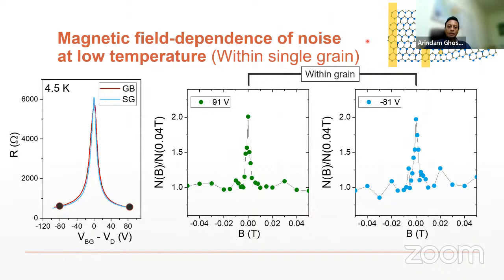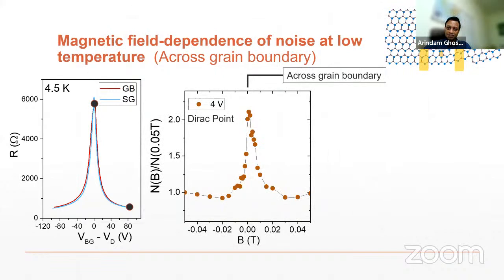However, if I do this at a grain boundary, now you can see there's a grain boundary here, and I'm measuring the noise across the grain boundary, and I'm going to show you two different gate voltages. One is at the Dirac point. You can see at the Dirac point, noise is going up by a factor of 2.